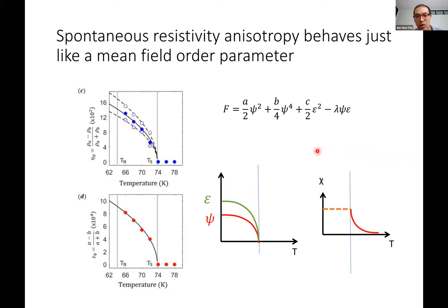So in this free energy, where you have the nematic order parameter as the primary order parameter and the strain as the secondary order parameter, what you expect is that you will have a spontaneous strain and a spontaneous order parameter, and they will have a ratio. And this ratio is actually the same number corresponding to the bare nematic susceptibility at the transition temperature. Remember that I mentioned previously that the bare nematic susceptibility will not diverge, but will reach a finite value at the phase transition temperature. It turns out that number is exactly the same as the ratio of the primary order parameter, the nematic order parameter, to the structural distortion.